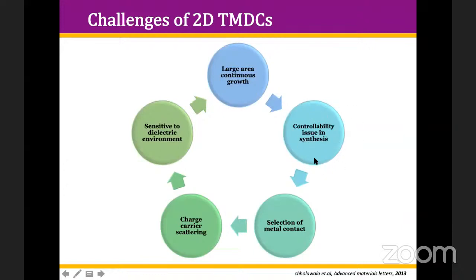After that, the ohmic contact or the Schottky contact, the selection of metal contact with 2D materials, is another challenge. Charge carrier scattering because of a lot of defects in the material itself is also a challenge, and they are sensitive to the dielectric ambient environment.